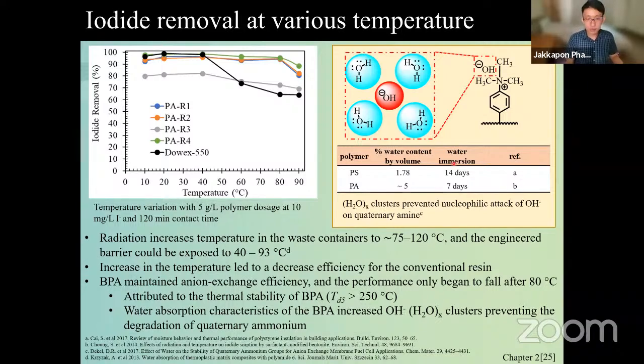With the water immersion test, we see that polyamide is better in water adsorption volume, and it can actually create a barrier, because this OH can actually degrade the chain right here. It can actually do the nucleophilic attack. So water barrier is very important. Molecular weight design is very important here. That's why at a higher temperature, my PA is a bit better than the polystyrene, okay?